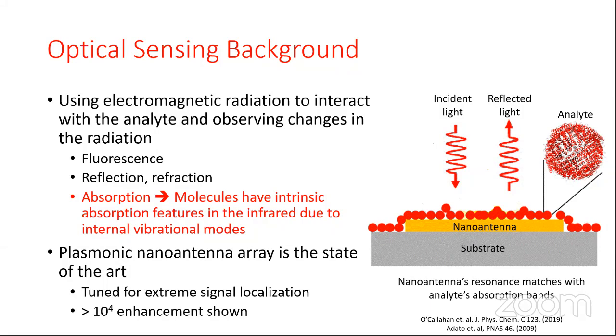And the state-of-the-art structure for optical sensing is the plasmonic nanoantenna array, and that's tuned for extreme signal localization. And people showed 4 orders of magnitude enhancement. On the top right, you could see a standard plasmonic-based nanoantenna. So on top of the substrate, we have the nanoantenna. In this case, it's a gold nanobar, and then an analyte covers it completely. And when shooting a light to the analyte and observing the reflected light, at resonance condition, the absorption will increase, so the reflection will decrease, and that will be proportional to the analyte concentration. And of course, the nanoantenna's resonance has to match the analyte's absorption band.